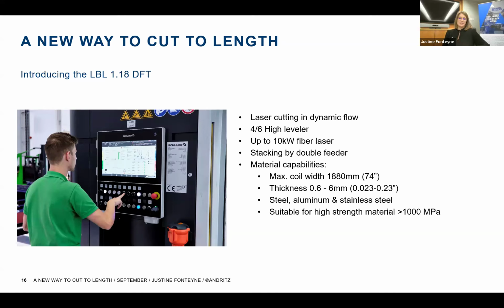Steel, aluminum, and stainless steel can also be processed, which is really interesting for those that are processing high strength material. Our laser blanking line has no problem with higher yield strength that are more than 1,000 MPa. As for the laser process, it does not really make a difference if it's higher yield strength or not, while for the mechanical systems, it does. So we have some customers that really choose the laser blanking just because of those increased high strengths.